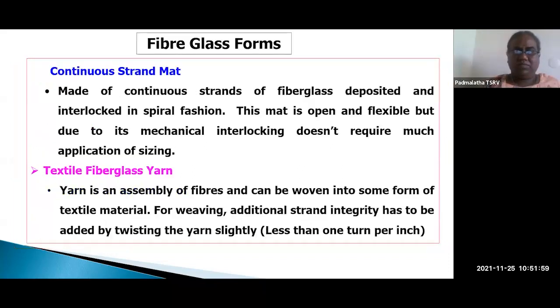Then continuous strand mat also will be there, made of continuous strands of fiberglass deposited and interlocked in a spiral fashion. That layer also we can see in our cooler plates. It is the last layer. This mat is open and flexible, but due to its mechanical interlocking, it does not require any chemical sizing or binder. So those are the strand mats, and even carbon also will be there as strand mats.